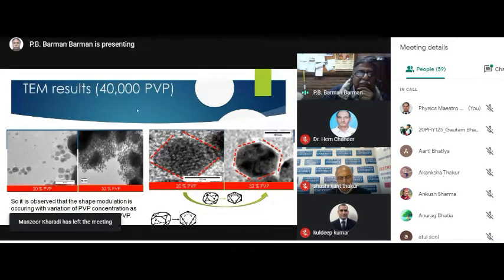This is the HRTEM result basically. You can see 20%, 32%, again 20% PVP and 32% PVP. This is practically what we have - the shape modulation occurring by variation of PVP concentration, as well as changing the molecular weight of PVP. Here we have chosen the molecular weight of PVP as 40,000.